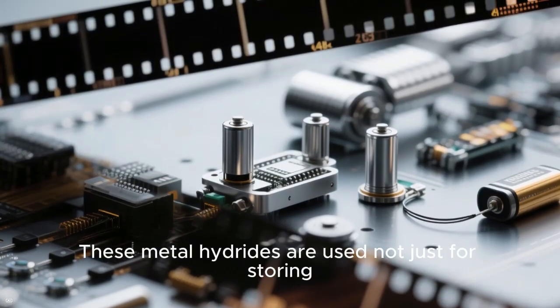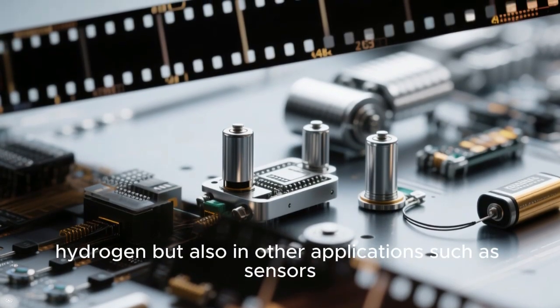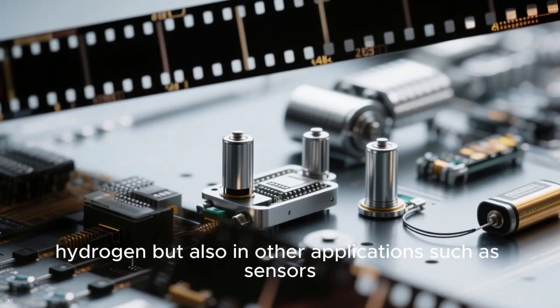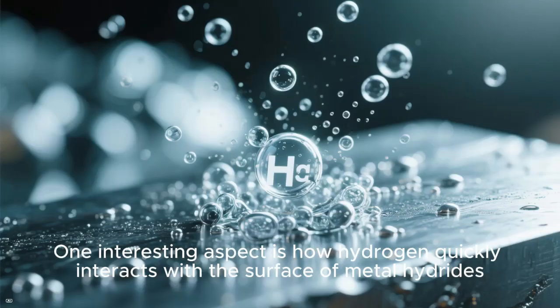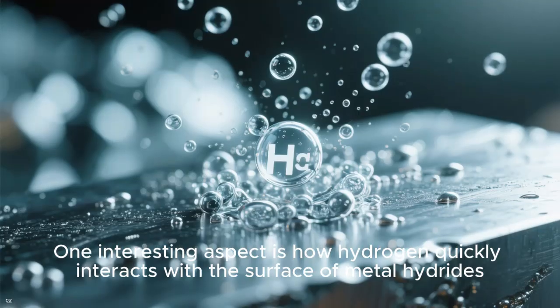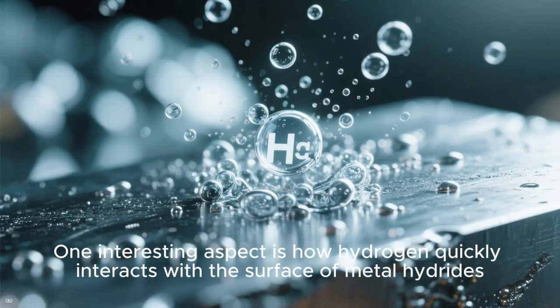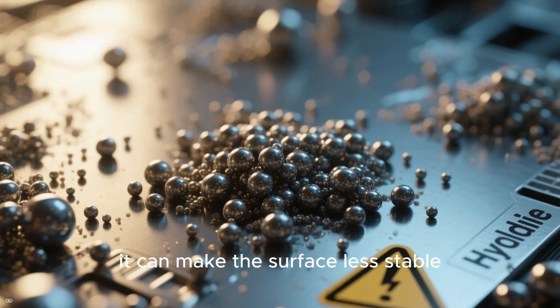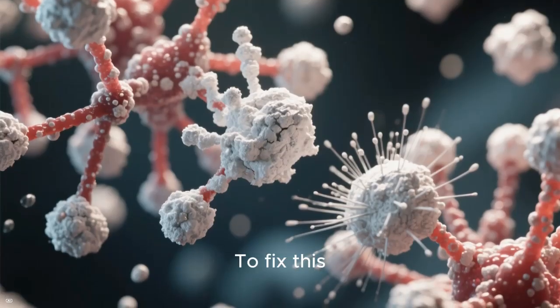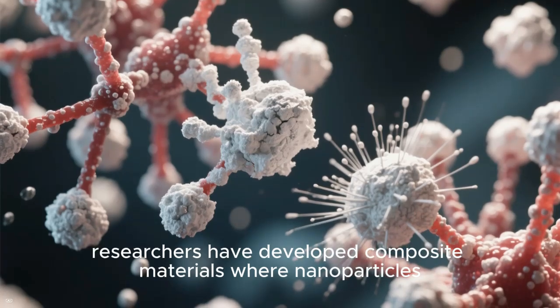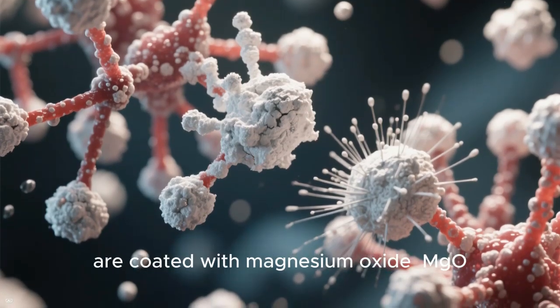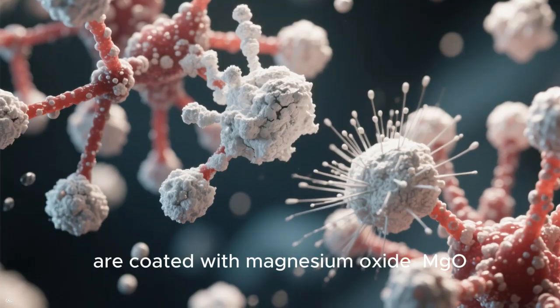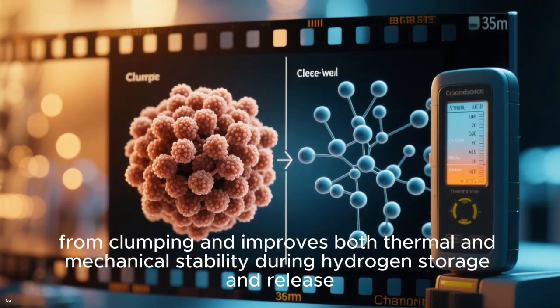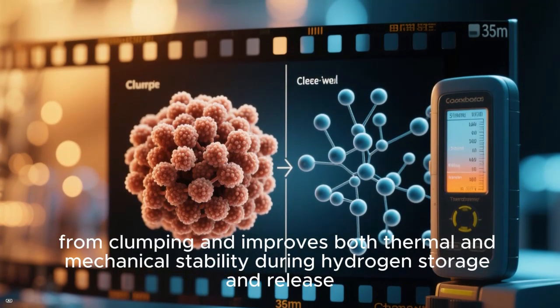These metal hydrides are used not just for storing hydrogen, but also in other applications such as sensors, switchable mirrors, and batteries. One interesting aspect is how hydrogen quickly interacts with the surface of metal hydrides. However, if the particles on the surface clump together too much, it can make the surface less stable. To fix this, researchers have developed composite materials where nanoparticles are coated with magnesium oxide. This coating helps prevent the particles from clumping and improves both thermal and mechanical stability during hydrogen storage and release.